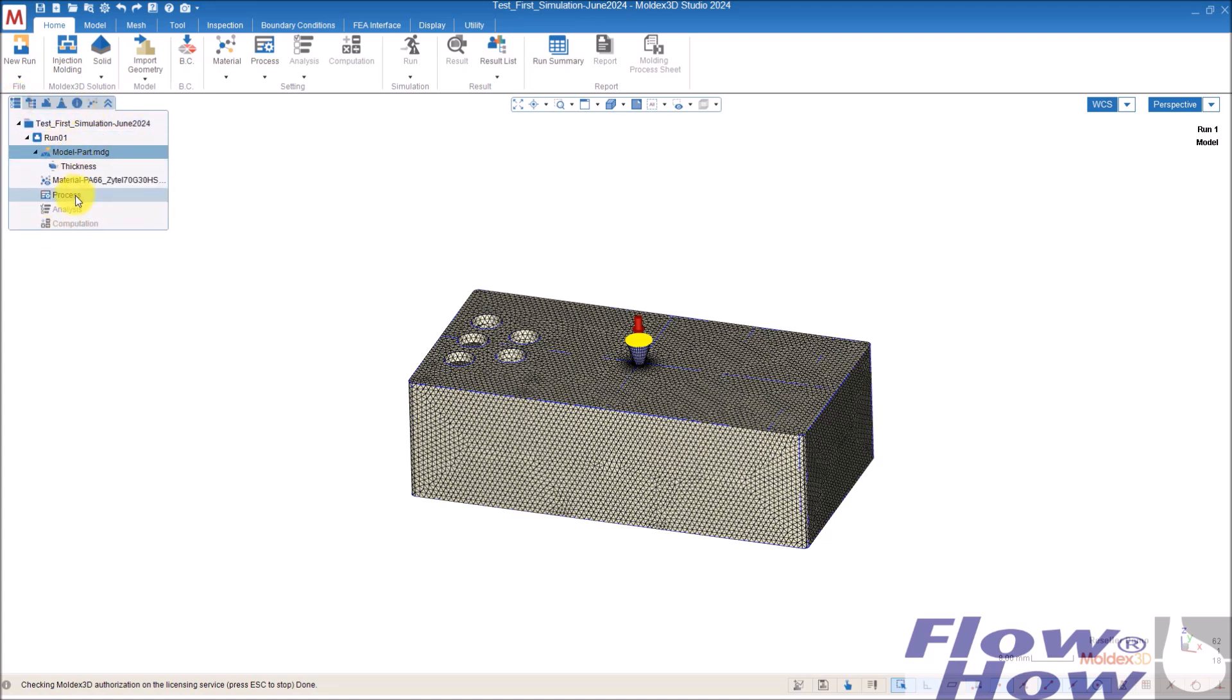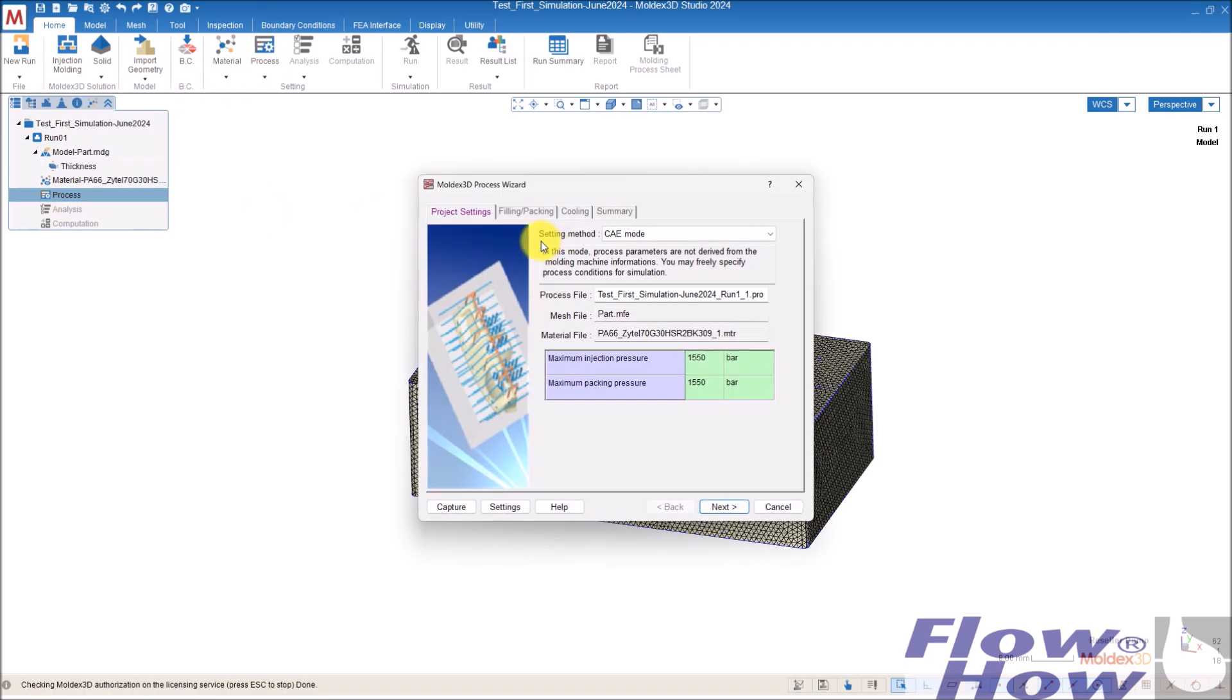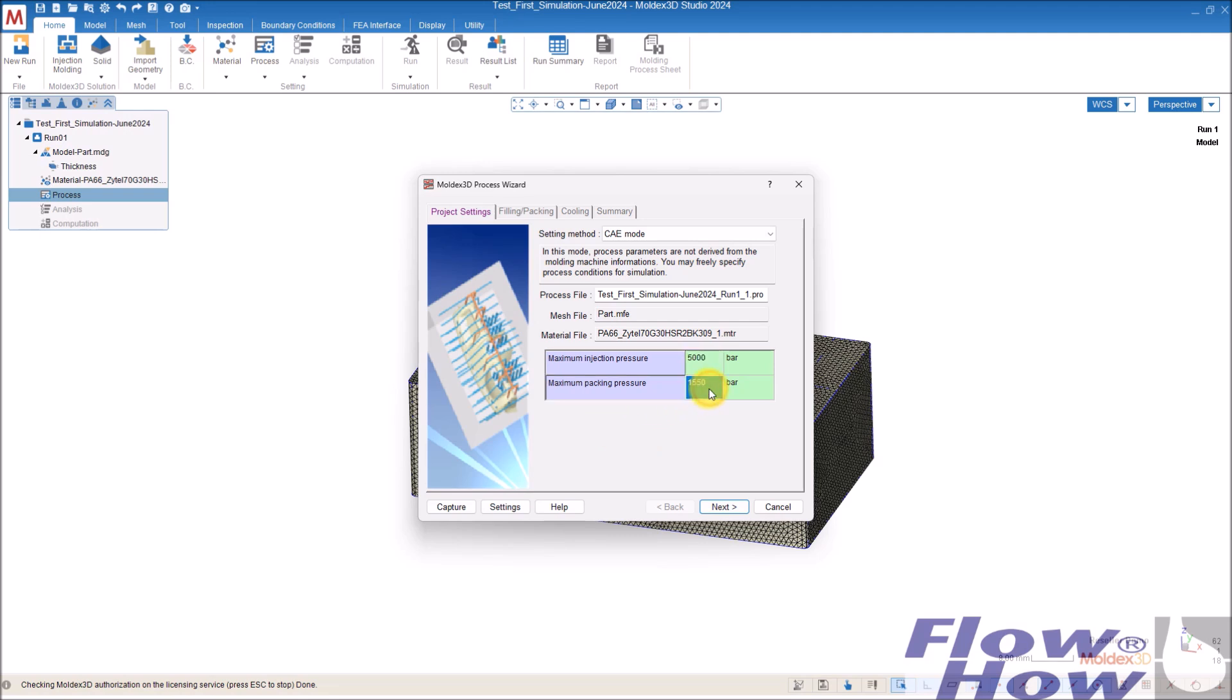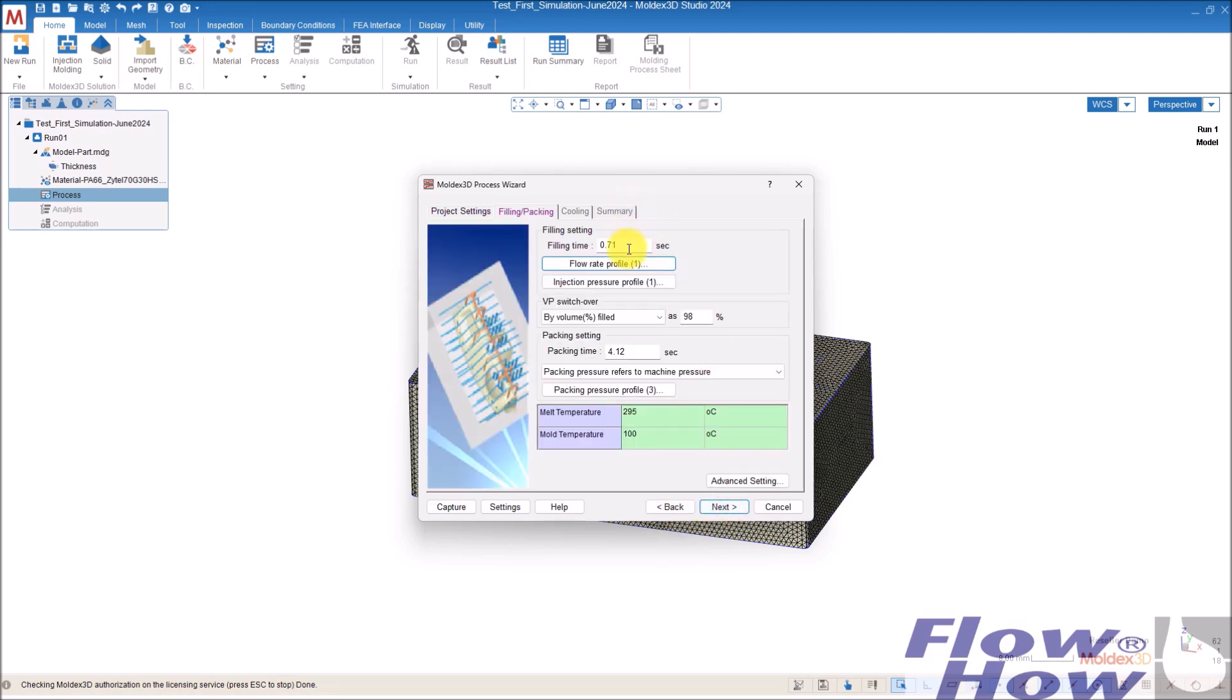And the process. Now we need to put up the process. I'll just double click here or click up here. And I use, for these kind of simulations, I use CAE mode. And then I put in some limitations of the machine, my molding machine. And I don't want any restriction in the filling pressure. So this is not the pressure that is used. It's only what the machine is capable of delivering. So I use 5000 bar. And the packing pressure, I don't need more than 1000 bar. So I give in that. And then I have the filling time. I also have a video of how to define the process defined by the simulation results. But anyway, the first time I guess the filling time.